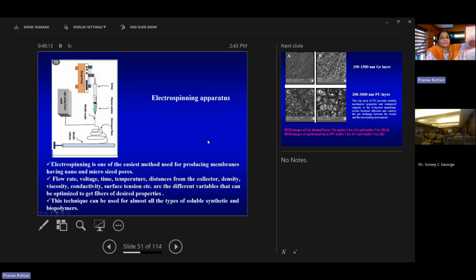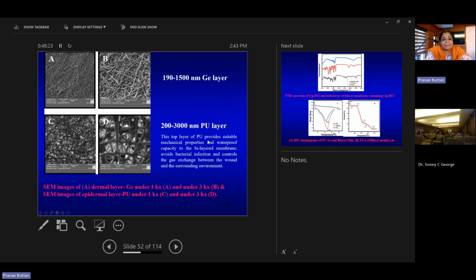So we developed the gelatin membrane first, and on top of that we coated this polyurethane membrane. So this is the SEM characterization. The first one is that of gelatin, and the second one is the polyurethane membrane. The diameters of the fibers are shown: 190 to 1500 nanometer diameter of the fibers are seen in the case of the gelatin layer, whereas 200 to 3000 nanometer diameter is seen in the case of the polyurethane layer.